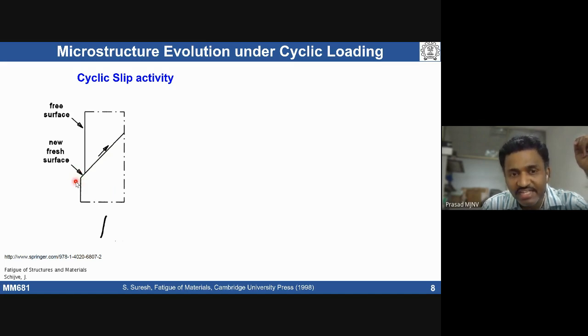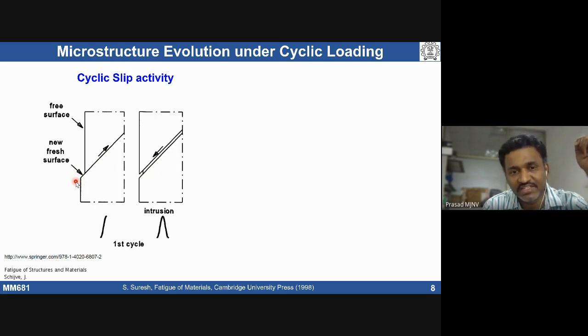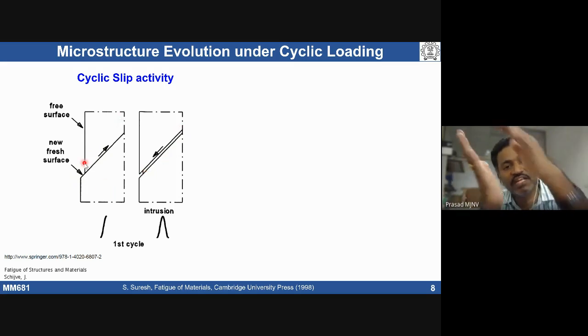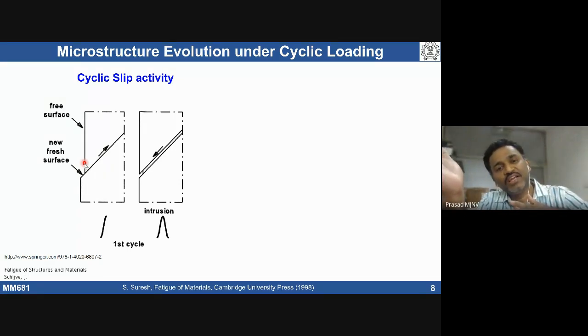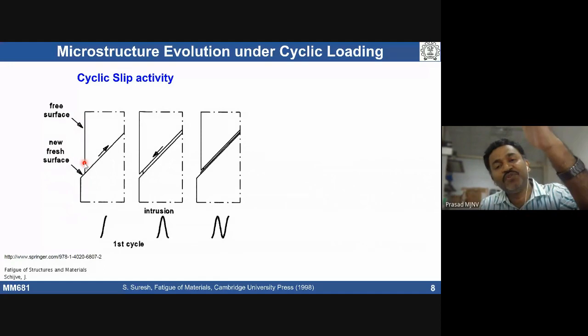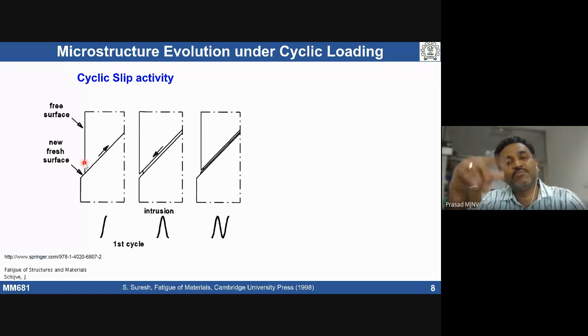When I decrease the stress, decrease means actually I'm applying stress in the other direction now. Assume that I'm applying tension-compression. So what happens again? On this surface, shearing activity now happens in the other direction. Again we see shearing activity, opposite. Depending on the tension or compression we are applying, I do see this kind of slip activity locally at certain locations, near some surface.